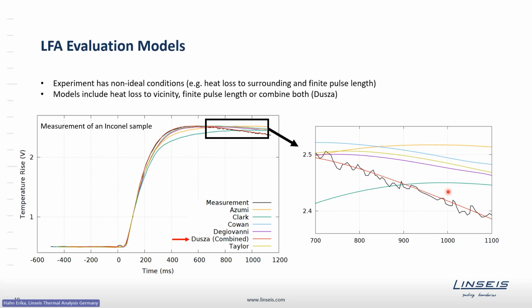But in reality, there are some non-ideal conditions like heat losses from the sample to the surrounding, to the sample holder, and so on. And the so-called finite pulse length effects. This happens for very fast samples, so for highly conductive samples where the measurement time is very low. These both effects need to be corrected, but most of the available models just consider one of these effects. Here, Linseis is quite unique, having this so-called combined model from Dr. Dusza, who considers both effects at the same time, and this is a more or less universal evaluation tool, being able to evaluate almost every kind of material.